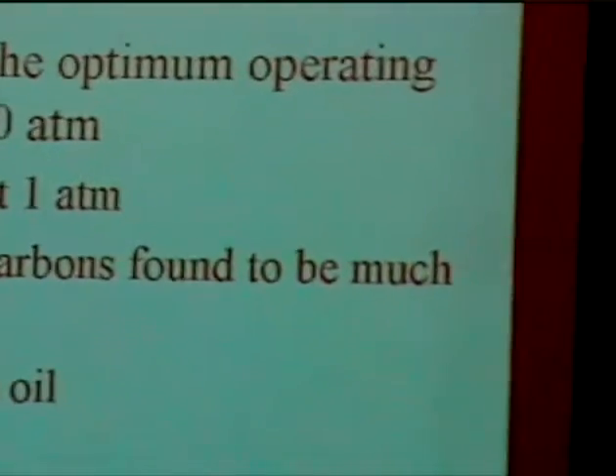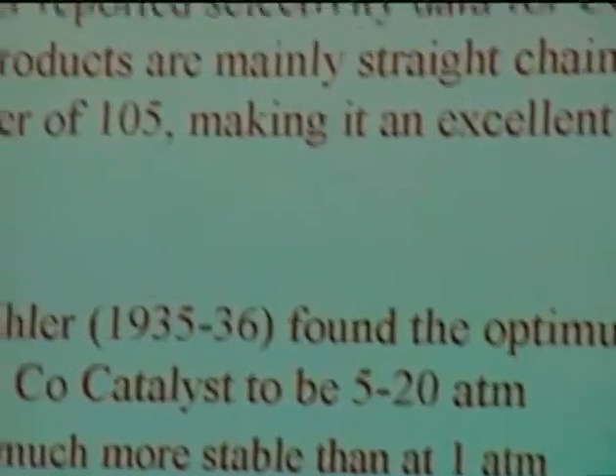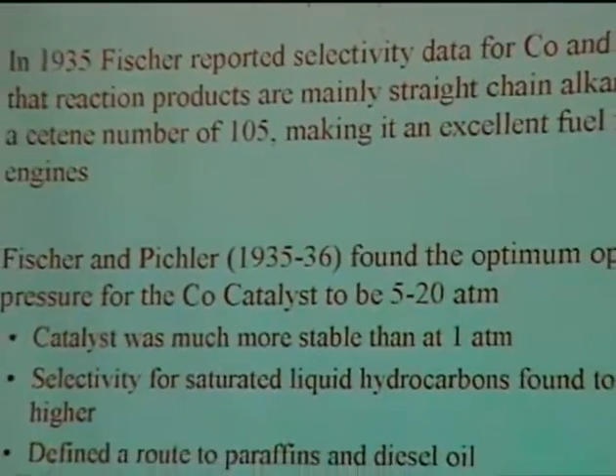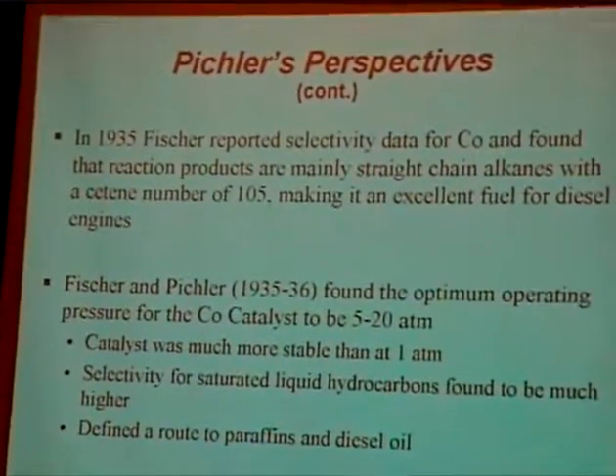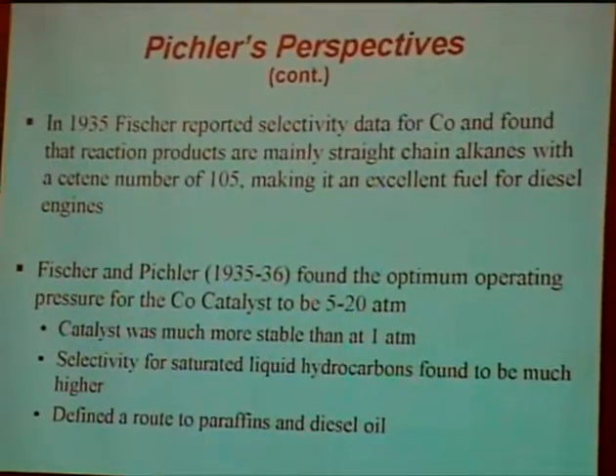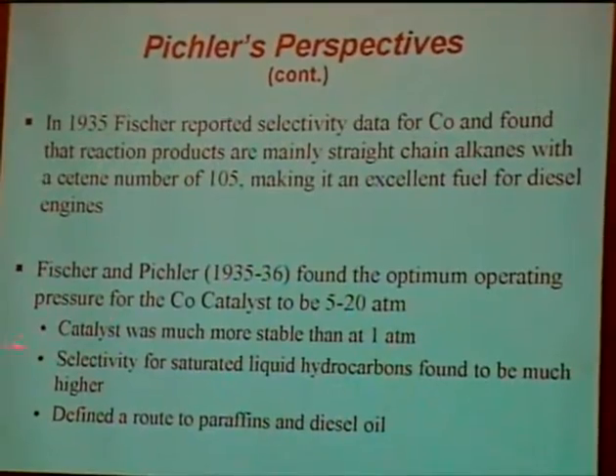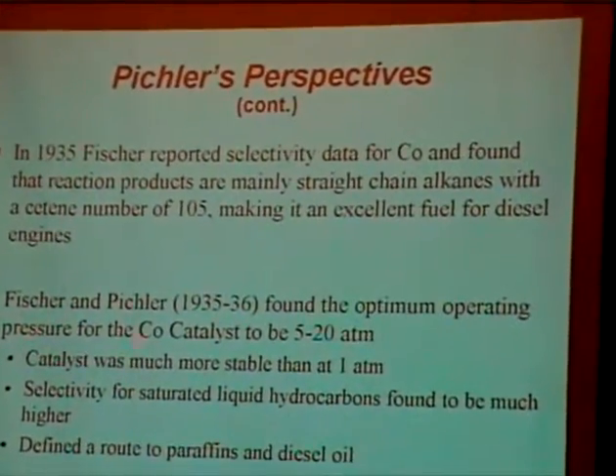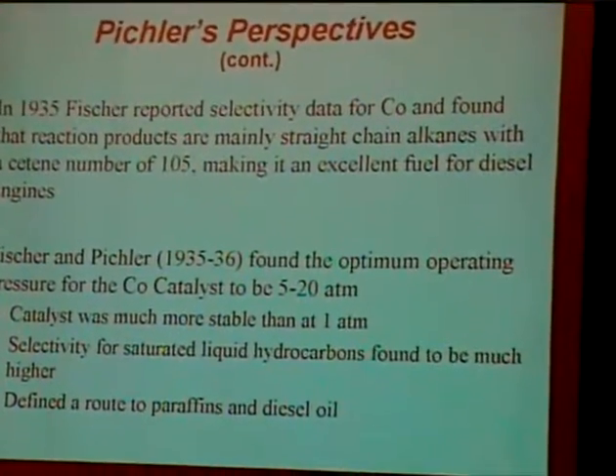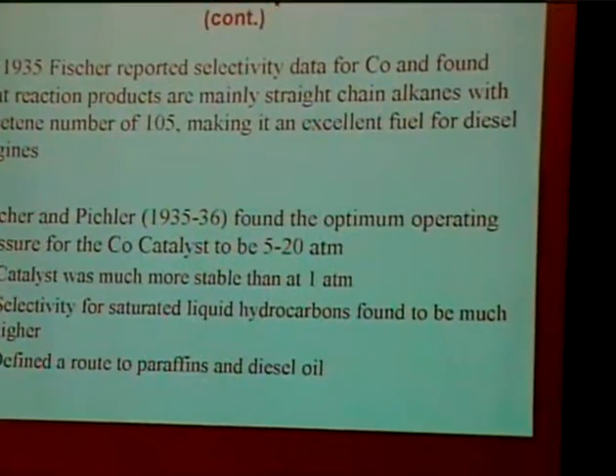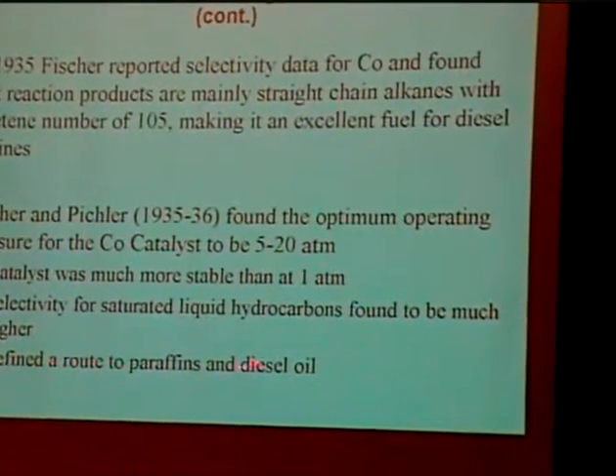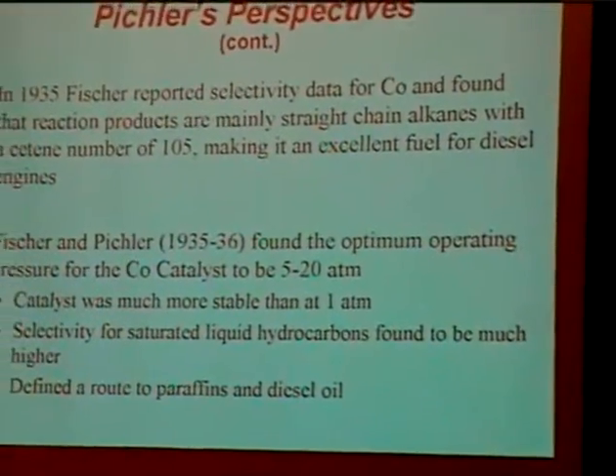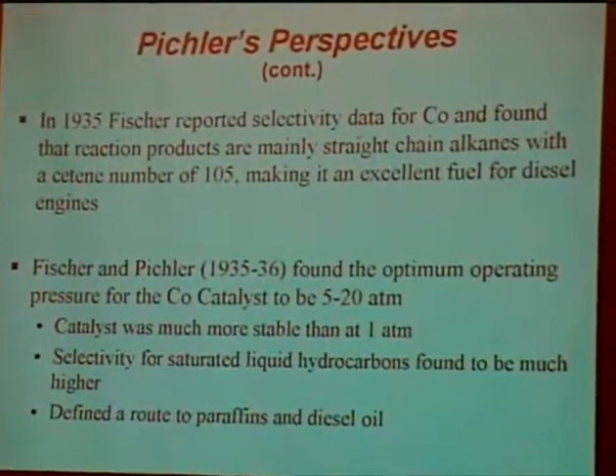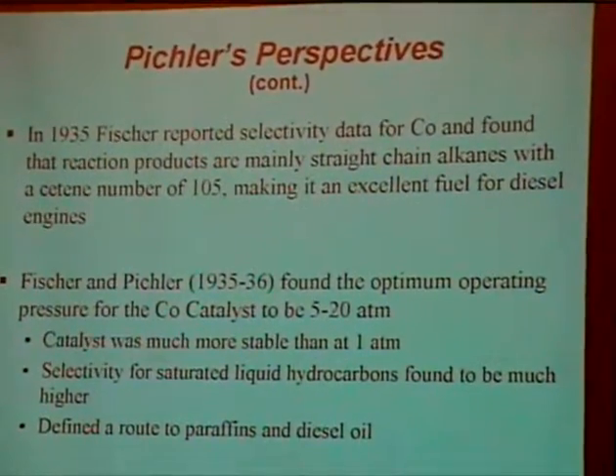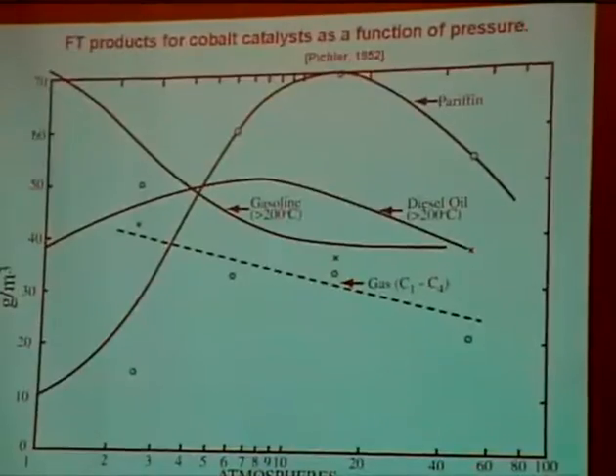Fischer and Pichler in '35 to '36 found the optimum operating pressure for their cobalt catalyst to be 5 to 20 atmospheres. Under these conditions, the catalyst was more stable than at 1 atmosphere, and the selectivity for saturated liquid hydrocarbons was higher, defining a route to paraffins and diesel oil.